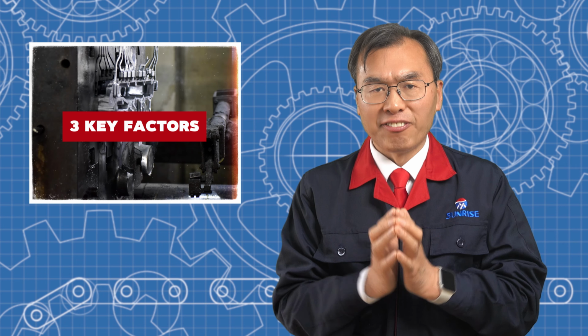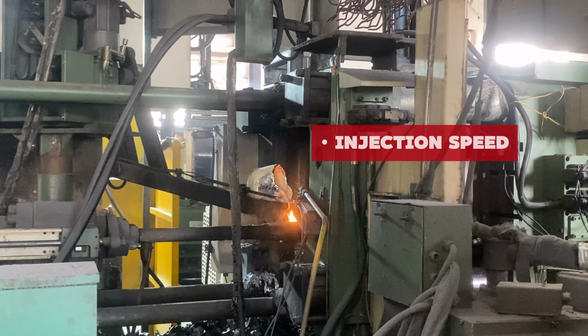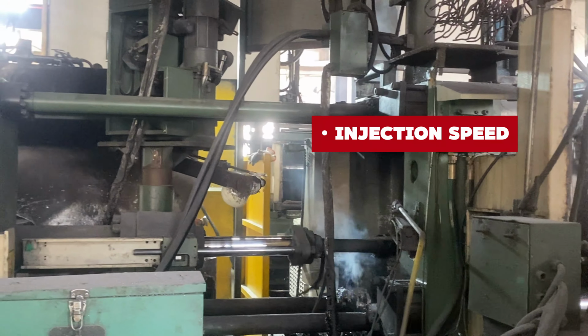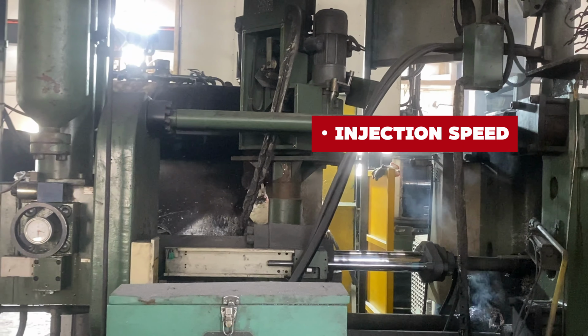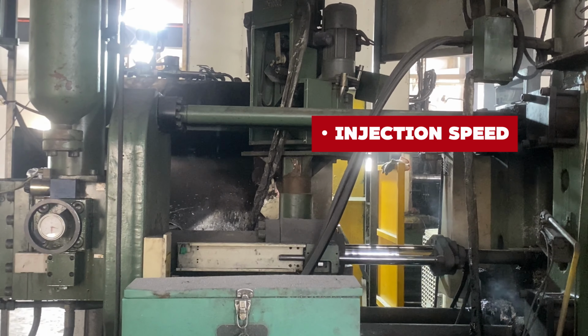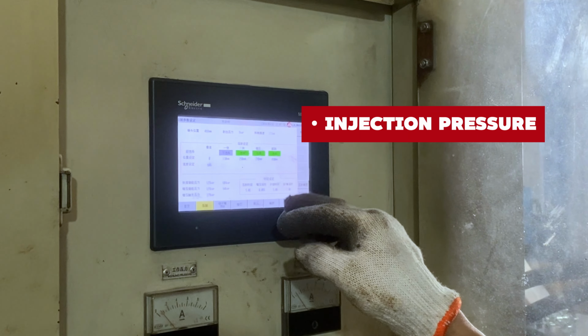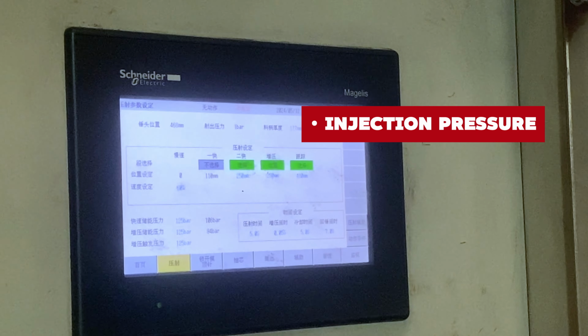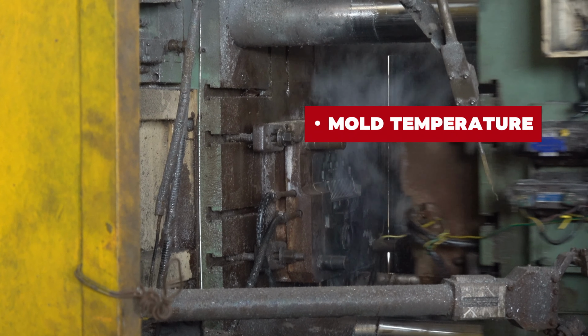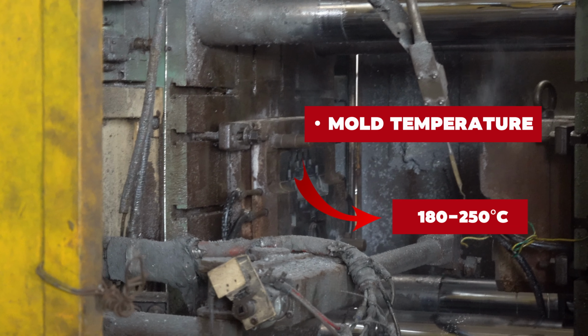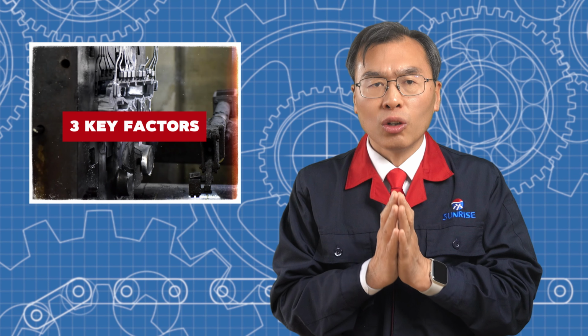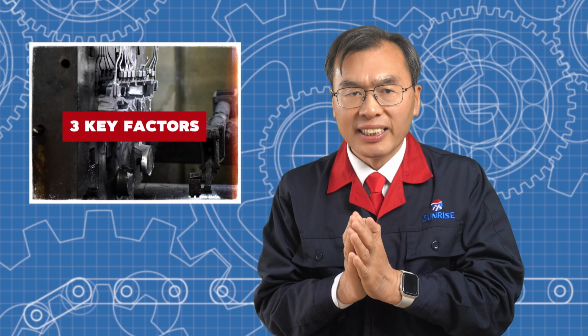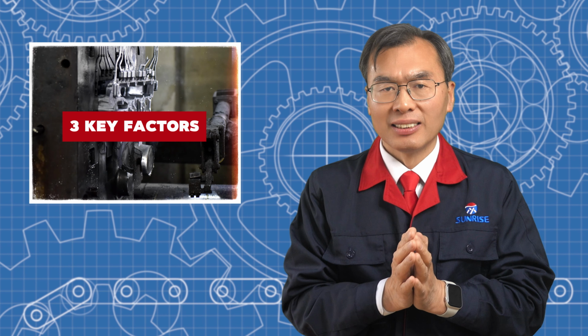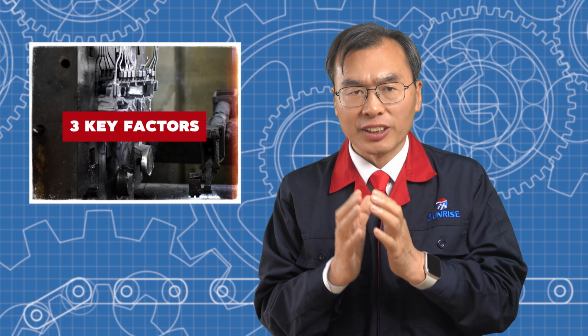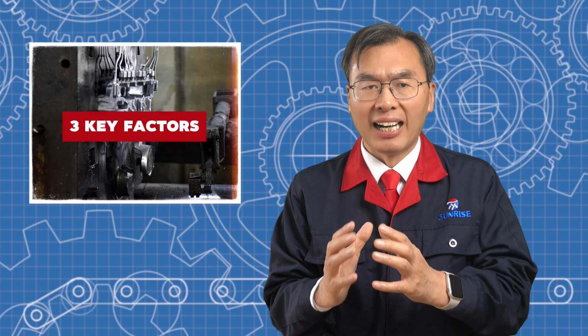Three main factors affect the quality of die-casting parts. Injection speed controls how the molten metal fills into the mold. It starts slow and then speeds up to prevent defects. Injection pressure is applied after filling to make the part denser and stronger. Mold temperature is usually between 180 to 250 Celsius degrees. If it's too low, defects can form. If it's too high, the mold can wear out faster. By adjusting these factors, manufacturers can produce strong, high-quality parts and extend the life of the mold.